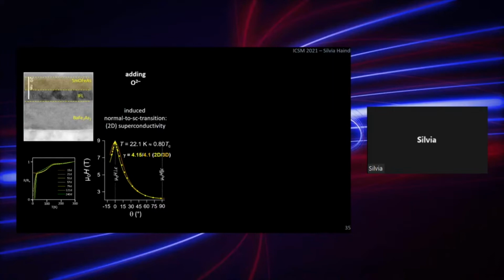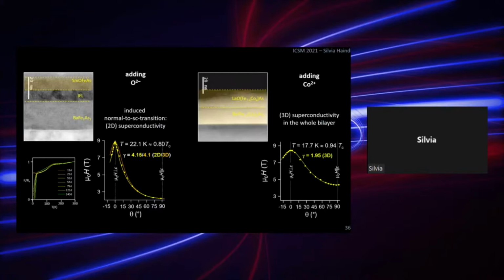But what we can say is, when we measure the angular dependence of the upper critical field, we definitely see a 2D behavior. So we can fit Tinkham's formula and see that the superconductivity is confined in the layer, and it should be the upper layer. This is in contrast to the cobalt doping, where we see the cobalt is diffusing from the top layer into the bottom layer down to the substrate. We finally see a 3D superconductivity state, so we have here the Ginzburg-Landau classical formula for 3D superconductors.